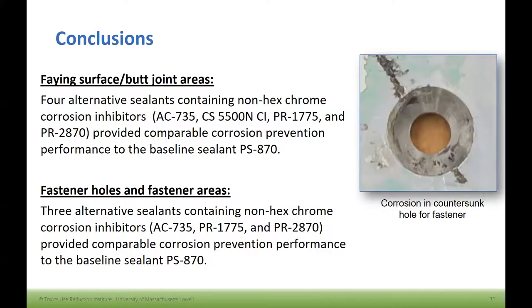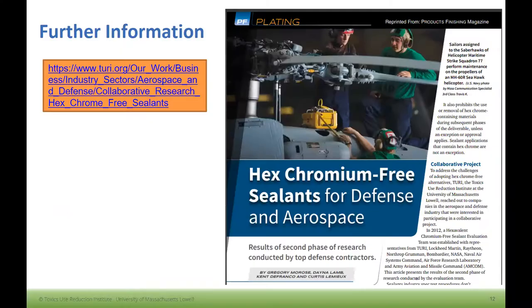So the results of all that testing. In the faying surface and the butt joint areas, four of the non-hex chrome sealants had comparable corrosion prevention performance to the baseline sealant that did have the hex chrome. So that was great. For the fastener holes and fastener areas, it's a little more challenging, but we did have three of the non-hex chrome products that had comparable results to the baseline hex chrome product. So overall, we have a number of different options that passed these corrosion tests for these companies to switch to. I covered this very quickly, but you can get a lot more details in an article that was published in Product Finishing and is available on the Terry website at this URL.